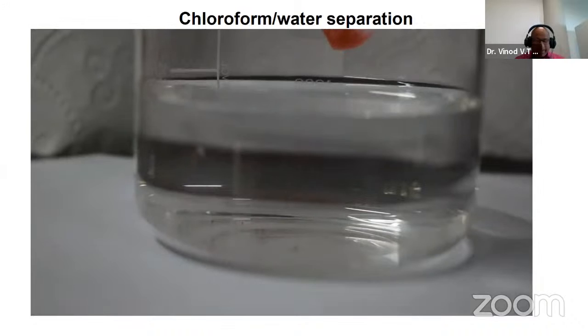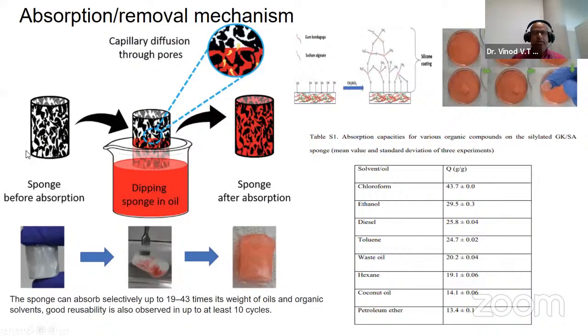How does it happen actually? What is the mechanism behind this adsorption? This is a simple capillary diffusion through the pores. As I showed in my earlier slide, this is a highly porous material. There is a lot of porosity in this sponge, so it can quickly absorb this organic solvent by capillary action. Later the material can be taken out by simple squeezing. Just press the sponge, and whatever was adsorbed will come out. So it can be recycled many times.